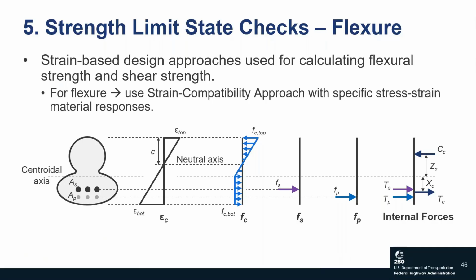In this approach, we start with an assumed strain profile. We use our stress-strain relationships for our different materials to go from strain to stress in our UHPC, steel, and pre-stressing. We take our stresses times our areas to get our force components, and then use equilibrium to adjust our neutral axis depth, and then ultimately calculate our moment and curvature that are associated with this.